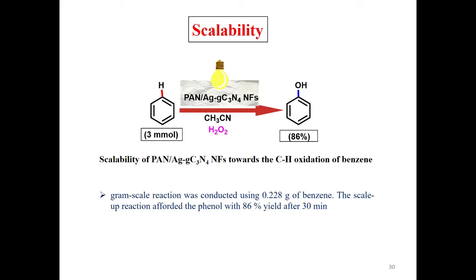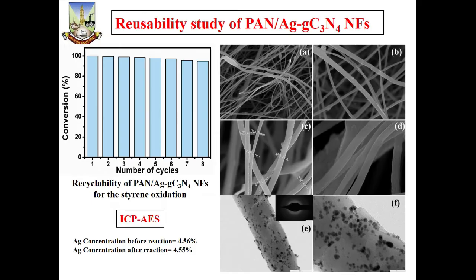So scalability, 3 millimole of reactant in presence of catalyst PAN Ag-gC3N4, simple light is being used, hydrogen peroxide, solvent CH3CN, there is a formation of phenol, which is converted 86%. This is how the reaction happened. Gram scale reaction was conducted using 0.228 gram of benzene. The scale up reaction afforded the phenol with 86% yield after 30 minutes.